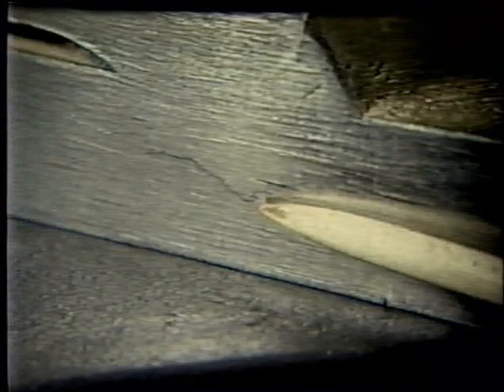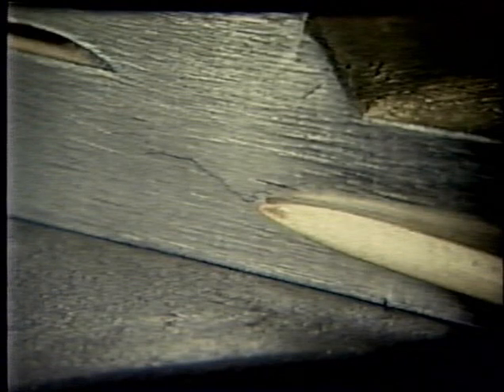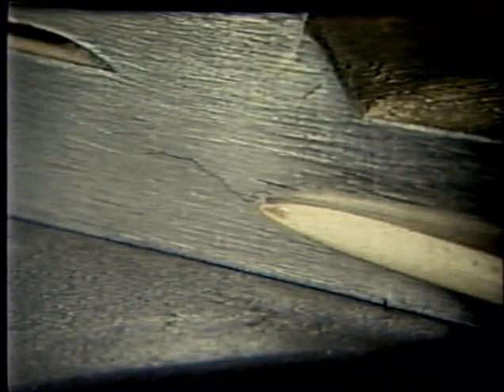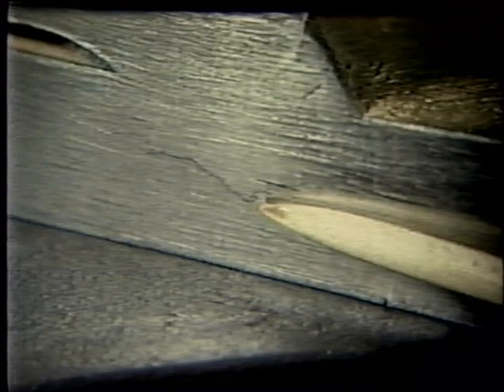Weld quality control does not stop with the verification of base and filler materials. In fabrication, conditions still exist that can bring about failure of the weld and base metal. Conditions including lamellar tears, excessive spatter, and arc strikes can occur in or on the base metal during welding operations. Lamellar tears are most common in heavier weldments. They are separations found within or beneath the heat-affected zone.